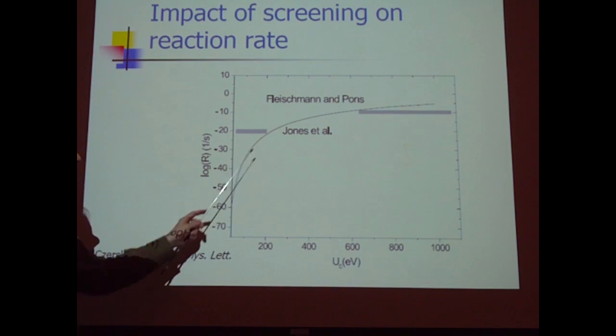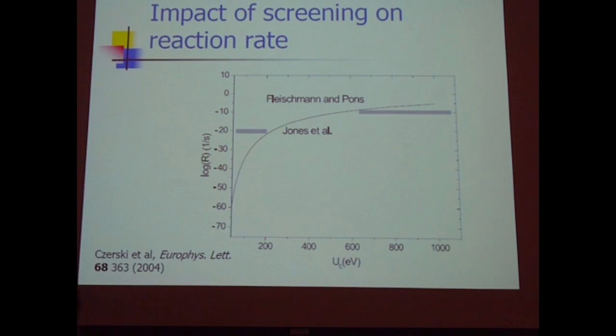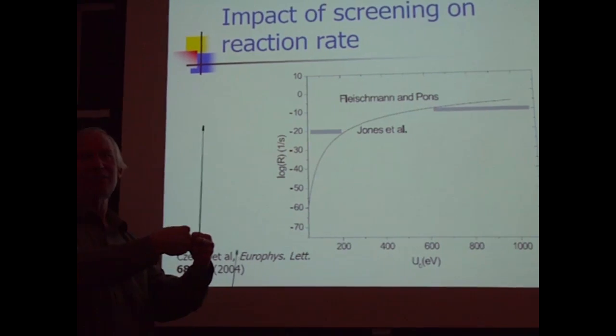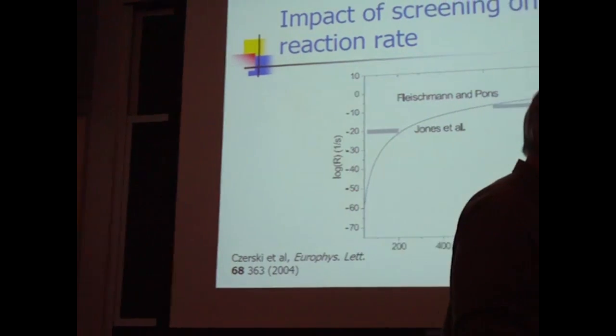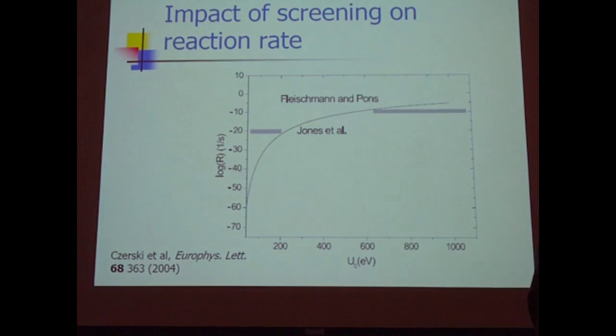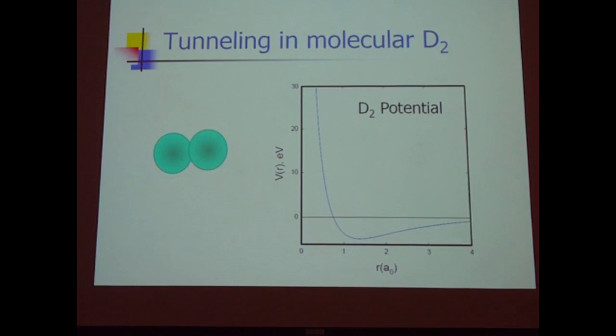But what this argues is that from the beam experiments, we know that there is screening showing up. You might say, well, maybe the kinetic experiment is a little bit different than the static experiment. The deuteron comes in, hits another one. Maybe when they fuse, they move. Maybe they go into outer orbitals of the nearby metal atom, and maybe that gives you more screening. But the Thomas Fermi screening numbers, those are substantial, and those you would expect in the static situation.